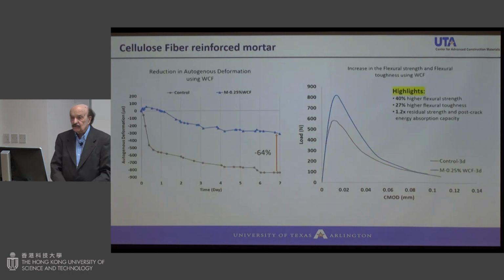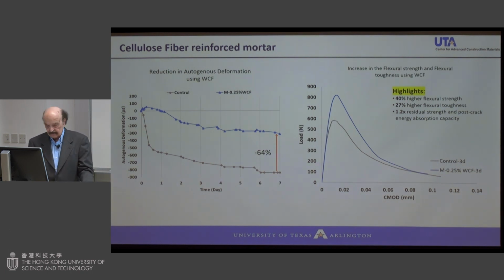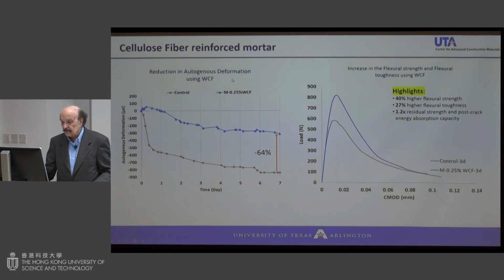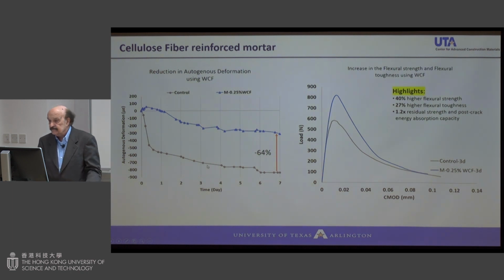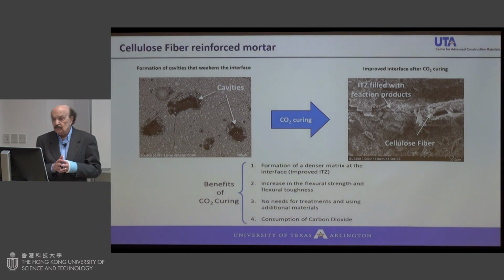Then we are also working on this waste cellulose fiber. I added this because Jishu here is also working on the natural fibers. These are waste cellulose coming from the paper industry. You can see, for example, his autogenous shrinkage with a control and a small amount of waste cellulose fiber. Similarly here, the load versus strain curve, control versus cellulose fiber. And we think that it can also help with carbonation.